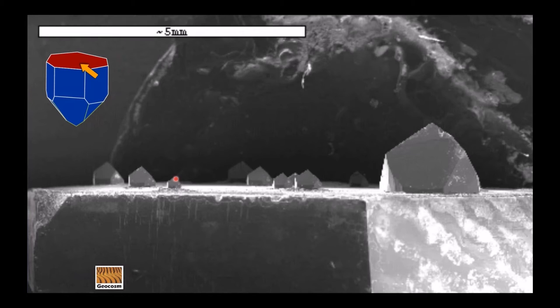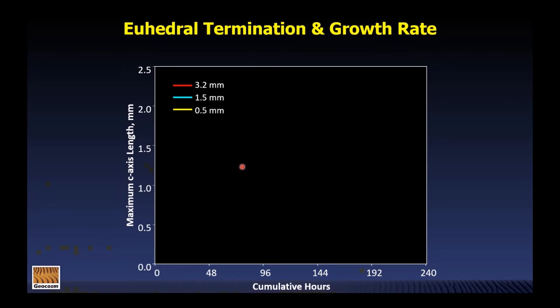Why did that happen? To address that, what we're going to do is take a look at the growth history of this big guy, one of these little guys, and an intermediate one. So in this plot, Dick Larisse, who did these experiments, every 2 days broke the experimental apparatus down, and he measured the length of those crystals, their lengths along that C crystallographic axis.